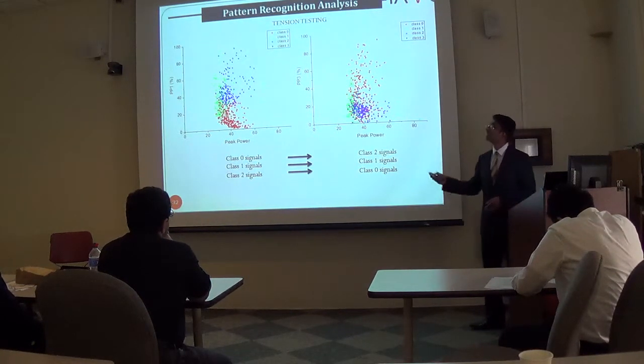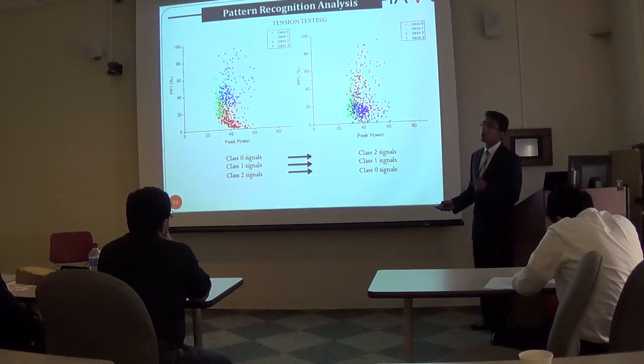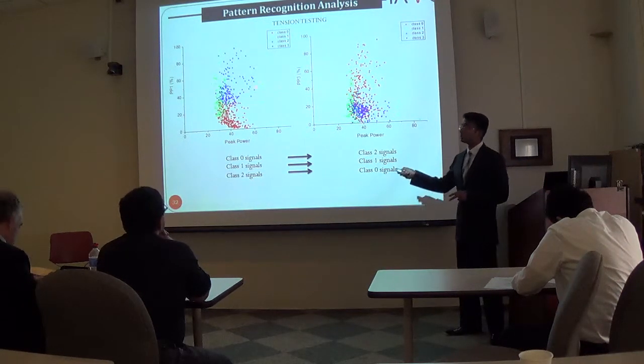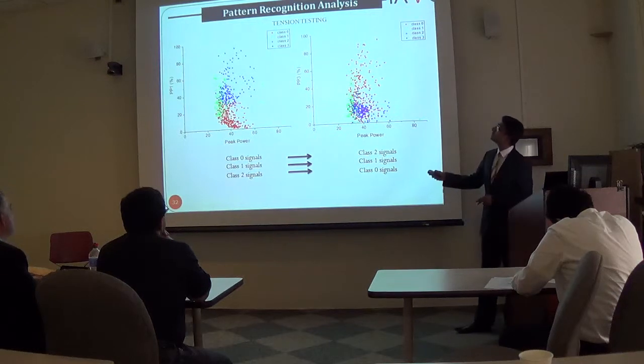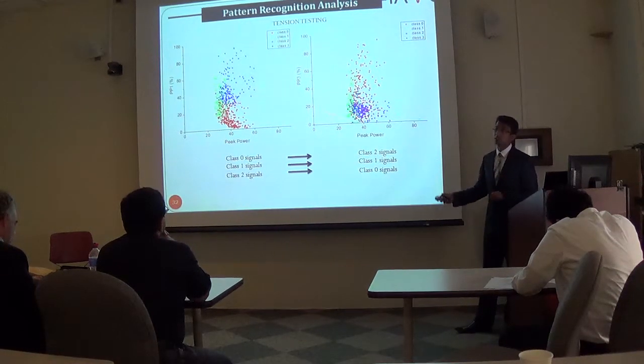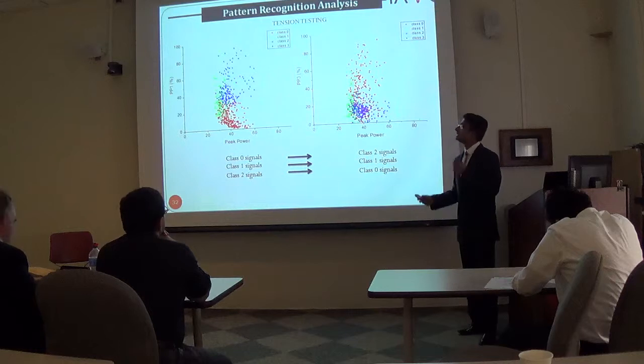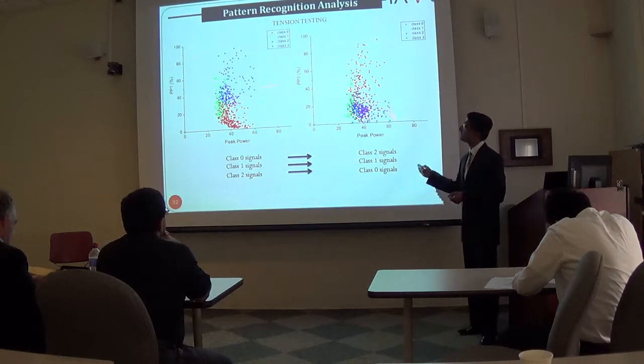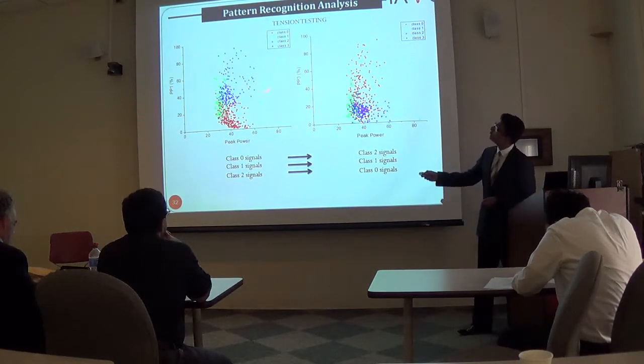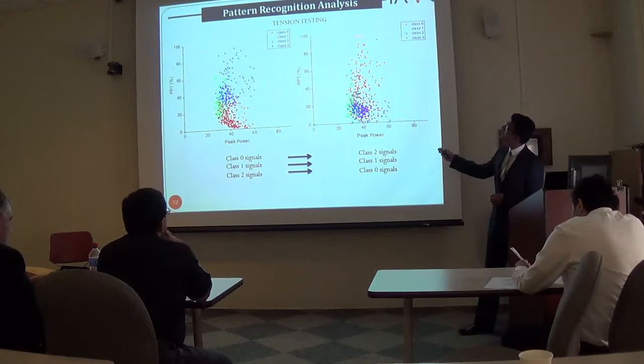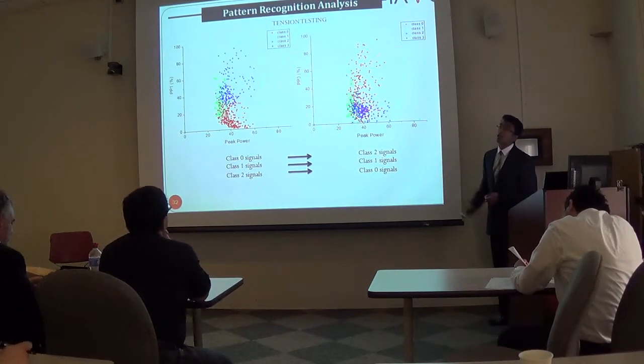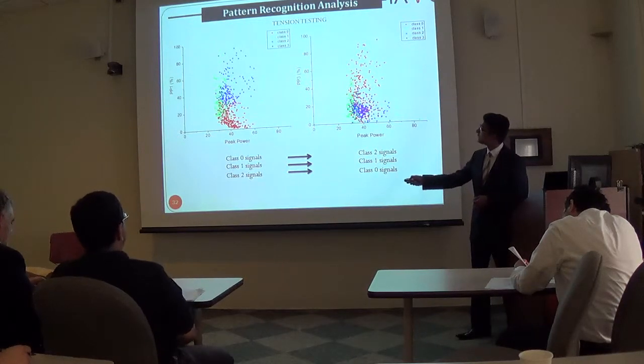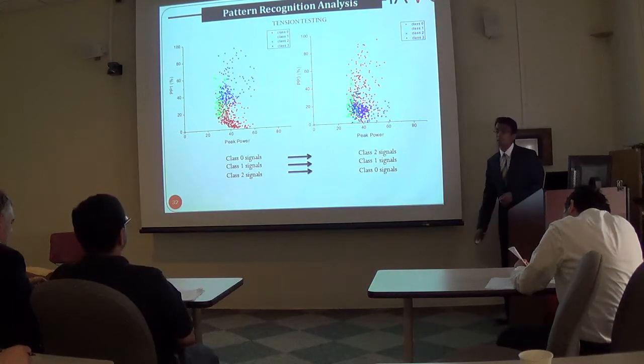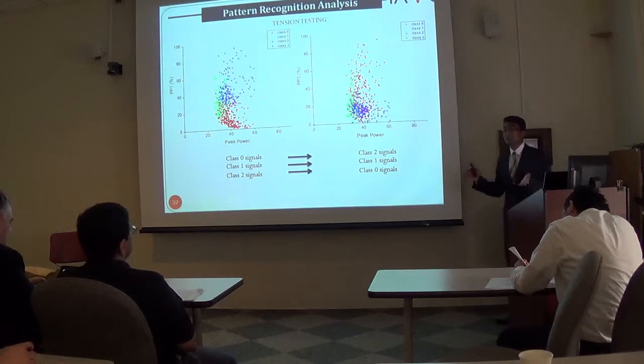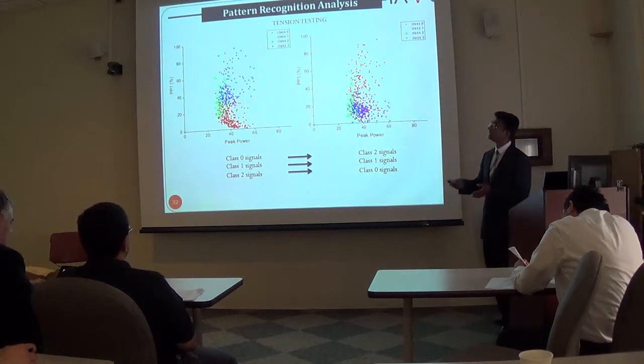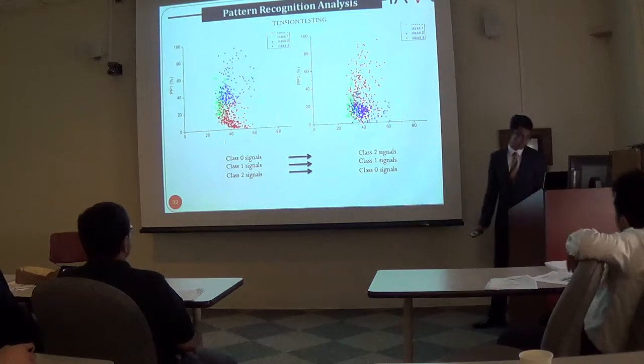And what is important to see here is this same pattern recognition analysis was applied on 2 different tensile specimens as shown here. What is important to understand is it's not important to match the colors between the specimens, but actually identify similar feature characteristics across the specimens. So as you can see here, the blue class, which is the class 2, seems to have very similar characteristics with the class 0, which is shown here, while the red class here, which is the class 0, seems to have a very similar class with that of class 2. So here you can see across the different tensile specimens, you can establish similar AE feature characteristics.